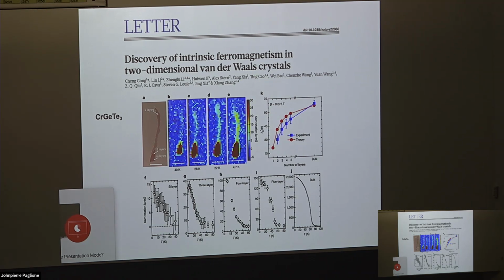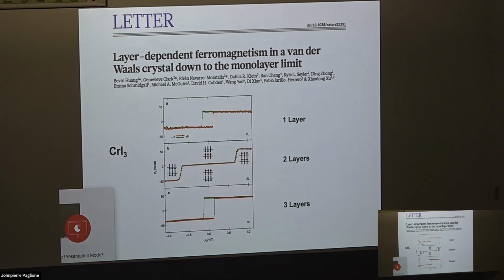So here's chromium germanium tellurium-3. And Cheng Gong is a professor here at the University of Maryland Electrical Engineering Department. He pioneered this measurement. He found single layers to be ferromagnetic. And probably the most famous magnetic one is this chromium iodine 3. They could see a nice hysteresis loop in one layer. They could see that the magnetism changed a little bit in 2 layers, then it was more similar to the 1 layer in 3 layers. All this stuff was worked out over the last 2 years. So yes, magnetism does exist even in single layer materials.